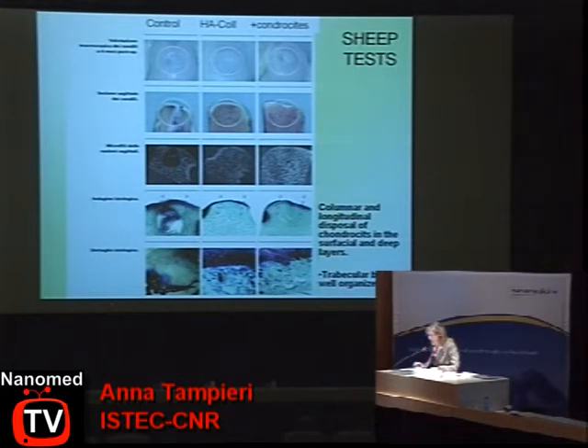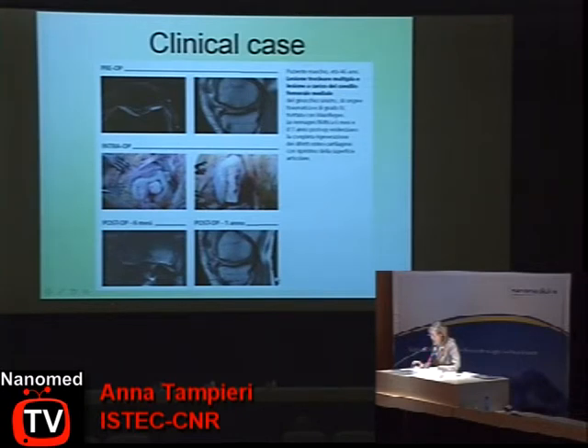Those are some sheep tests in which we compare a control without scaffold, the biohybrid composite, and the biohybrid composite plus chondrocytes, and in those last cases we have very good results. We have columnar and longitudinal disposal of chondrocytes and well-organized trabecular bone. This biohybrid composite was industrially developed by Finceramica Faenza, and it was brought up to CE mark. And so we also have a clinical case. This is a multiple trochlear lesion, and there is a follow-up at 6 months and 1 year, and the results were really good.